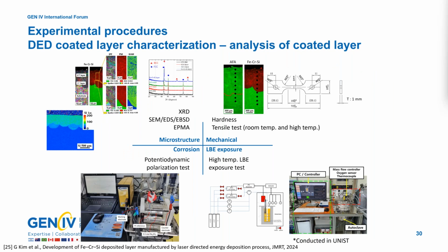The DED coated layers were characterized through microstructure observation, mechanical testing, and corrosion property evaluation, including high temperature LBE exposure test. The detailed results of these experiments are documented in the referenced research article.